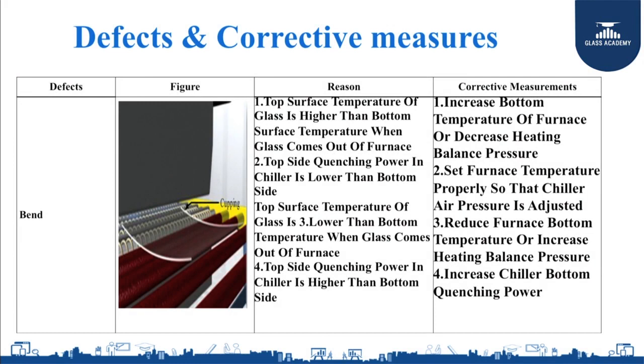Bend observed in glass. The reasons are very simple. Top surface temperature of glass is higher than bottom surface temperature when glass came out of the furnace. Top side quenching power in the chiller is lower than bottom side. Corrective measures are increase bottom temperature of furnace or decrease heating balance pressure. Set furnace temperature properly so that chiller air pressure is adjusted. Reduce furnace bottom temperature or increase heating balance pressure. Increase chiller bottom quenching power. These corrective measures will make sure that bend in glass is avoided.